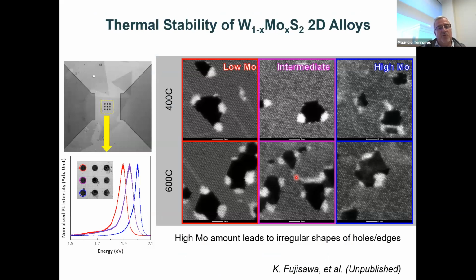So one thing that I think is important to look at, and this is something we did, some experiments we did with this structure. So this is the triangle. This is how we heated this triangle. The outside of this triangle is rich in tungsten. The inside is rich in moly, and you have an intermediate phase. So you can see low moly. So that's the edge. The moly atoms, they look like darker spots. In the intermediate phase, we have tungsten and moly. What you can see, the bright and darker spots, that's moly and tungsten. And when you have a high ratio of moly, you can see lots of the darker spots dominating there. So this is like having an alloy like 50-50, right? Or intermediate, where you have more tungsten here, but here you have tungsten and moly.